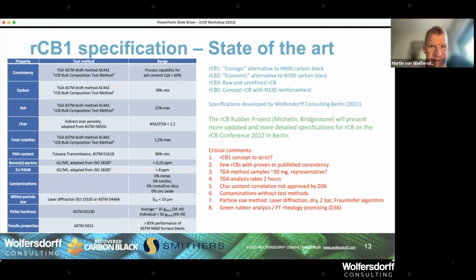To be honest, there is almost no company that is fulfilling this specification. Many companies come very close in many regards, but some companies, as I mentioned, the consistency has to be proven on the industrial system. So 10 micron milled particle size. Here, I'm saying laser diffraction, ISO standard or the ASTM standard. We now know we need to define more, and that is in the comments.